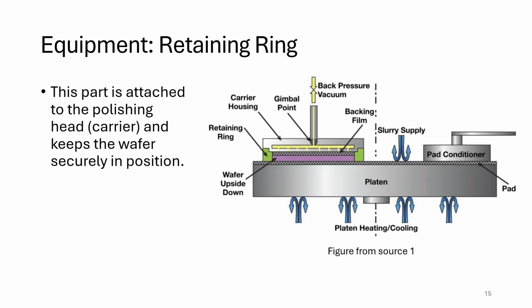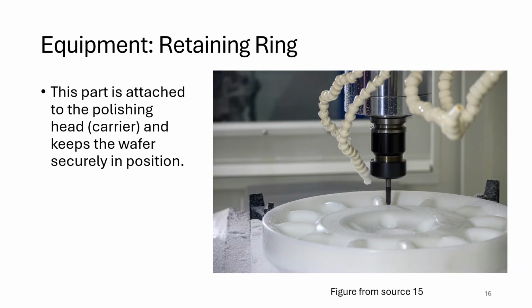The retaining ring, shown as the green part in the sliced image, interfaces with the carrier head. It centers the wafer on the carrier and helps to control wafer contact on the polishing pad, slurry interactions, and process stability. Its material, height, grooves, and wear govern edge removal and exclusion width. As rings wear, edge behavior can drift with exclusion widening or roll-off worsening, so tracking ring wear and groove integrity is part of keeping wafer-to-wafer uniformity controlled.